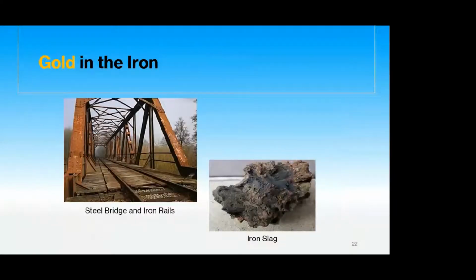Once the surface ores were consumed and the iron concentrations began to drop, miners avoided or tried to avoid the ores that contained the sulfide minerals. If they could not be avoided, then the miners roasted the ores to reduce the amount of sulfur they contained to make a higher quality cast iron. After the sulfur was driven off by roasting, the gold likely remained in the iron ore, which was then fed into the furnaces. Research performed by the U.S.